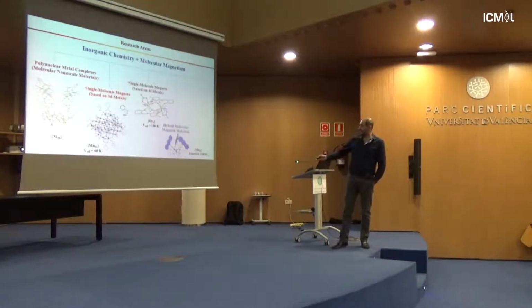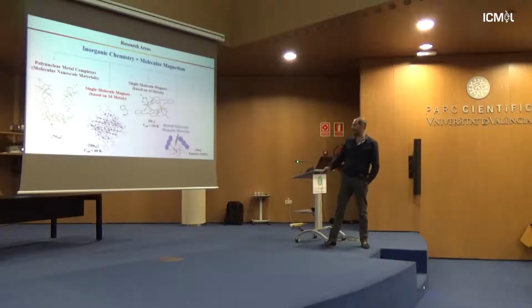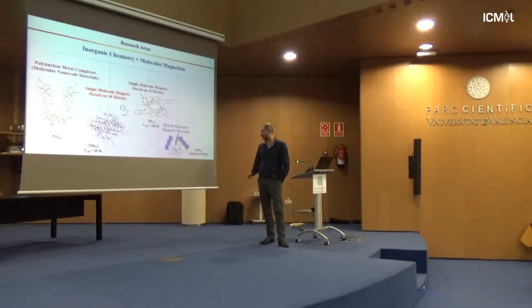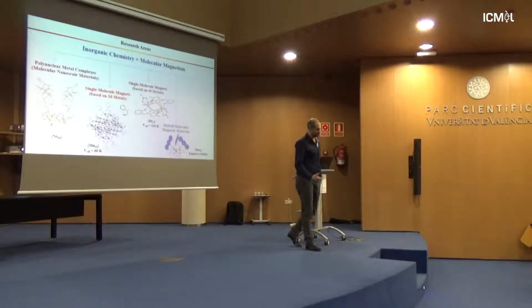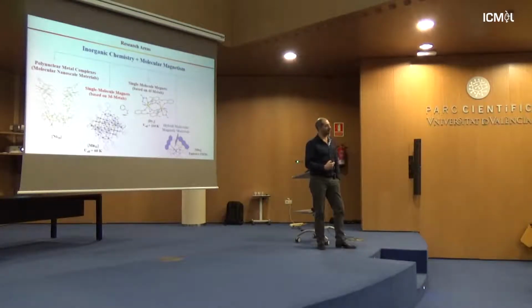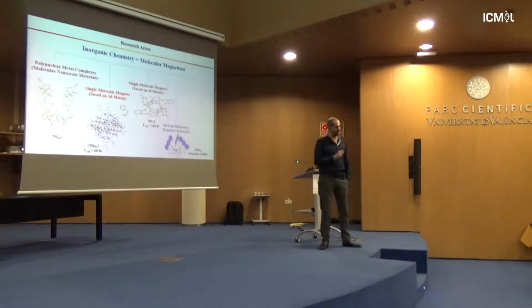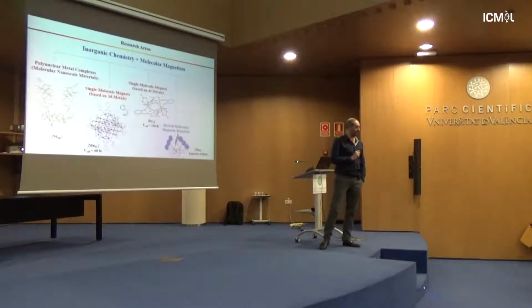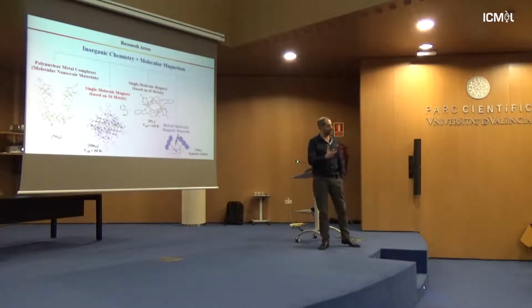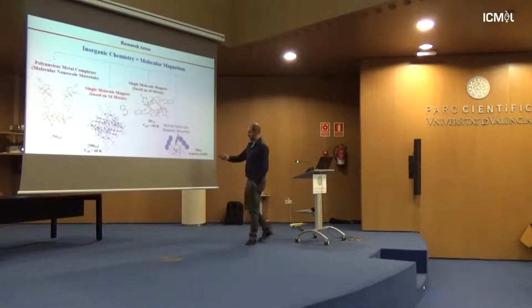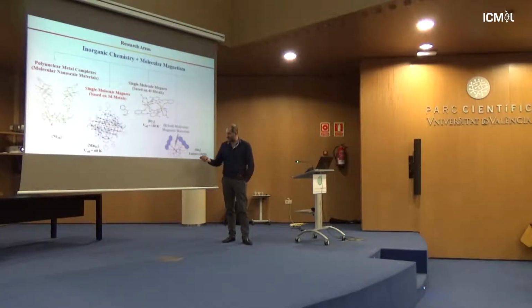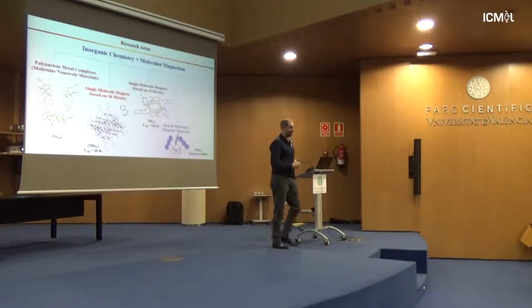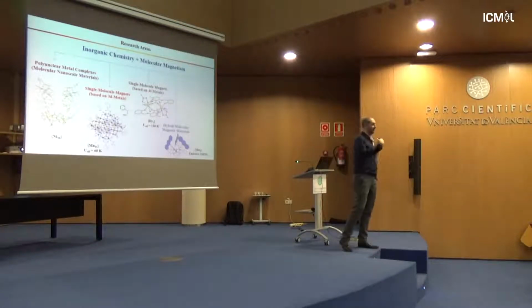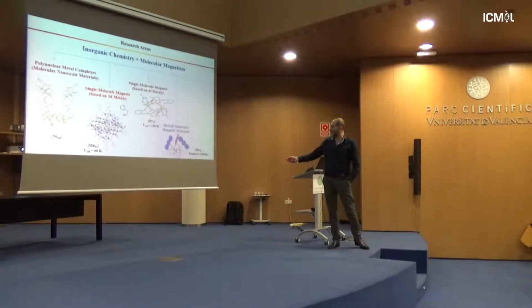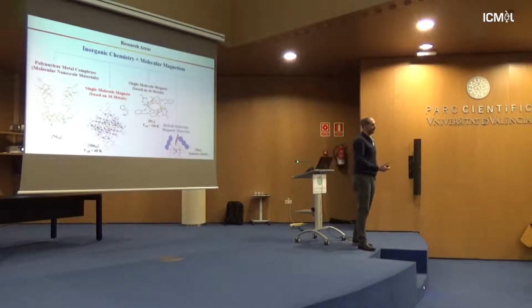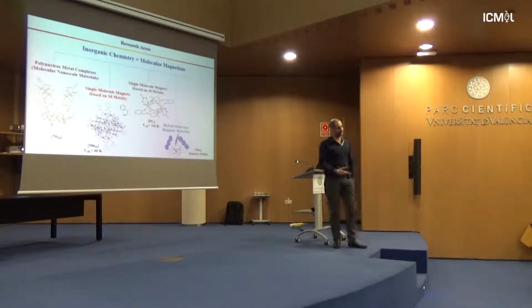So the next thing in that ranking of compounds is something that we recently tried to develop, the molecular hybrid magnetic materials, molecular compounds which can include more than one physical property within the same compound. It's not easy, especially with transition metals, which are known to quench the emission or photoluminescence properties. Regardless, we have been able to take that magnetic SMM unit, which is a manganese 3 triangle, and change the innocent carboxylates, which do not essentially do anything to the optical properties, with some optically active carboxylates, like pyrene, anthracene, fluorene, we have the coumarin, we have the naphthalene derivatives.